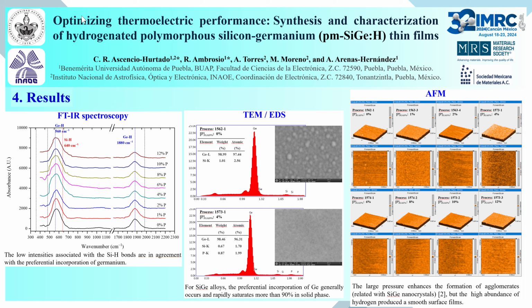Many results in literature were reported for undoped hydrogenated amorphous silicon-germanium, and all of them showed that as the pressure increases, the average roughness also increases. In contrast, our results show that the mean roughness values are always below 0.7 nanometers, regardless of the phosphorus concentration and high deposition pressure. On the other hand, the TEM and STEM mode top view micrographs and EDS spectra show